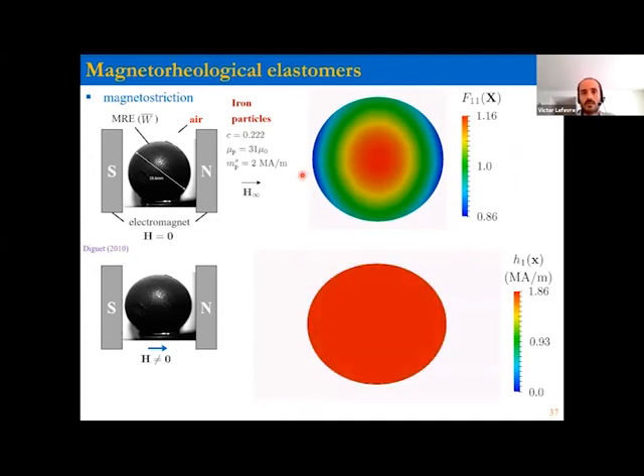And so this is plotted with respect to the undeformed configuration. So the sphere, it's a cross section of the sphere, so a circle. And you see that it deforms a little bit. That's the deformed configuration. There is an important thing to mention here. It's the fact that the fields in such an experimental setup are not uniform.